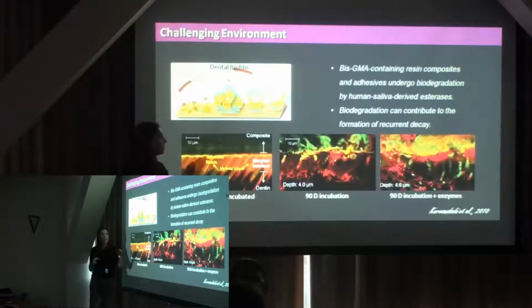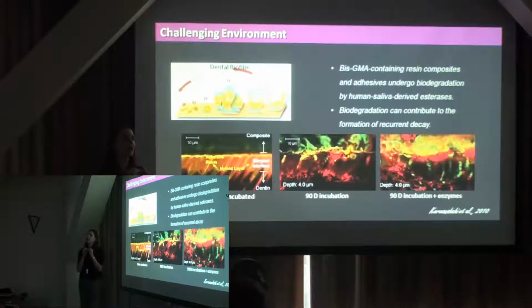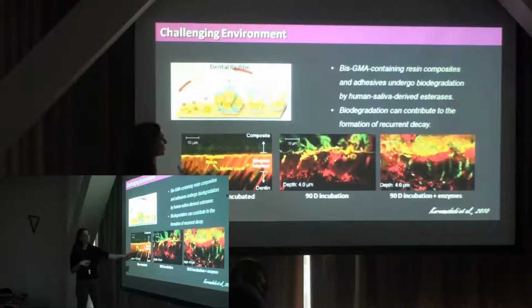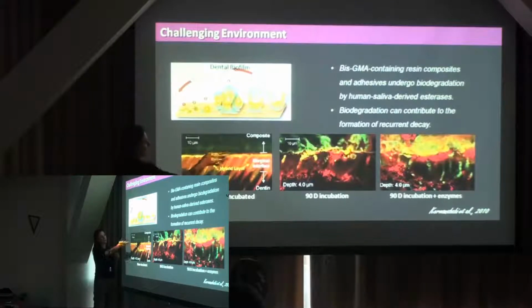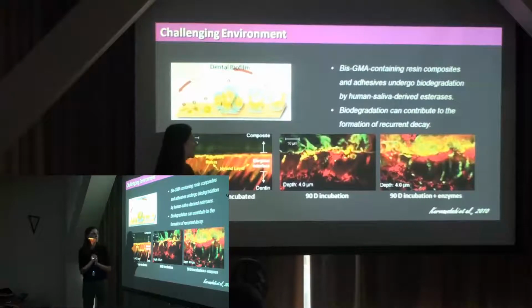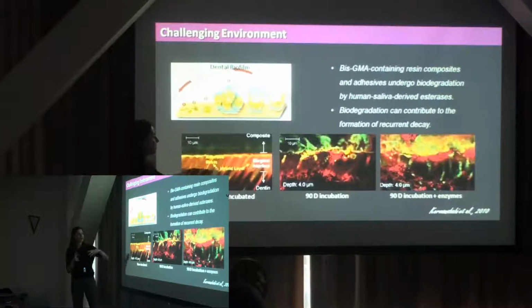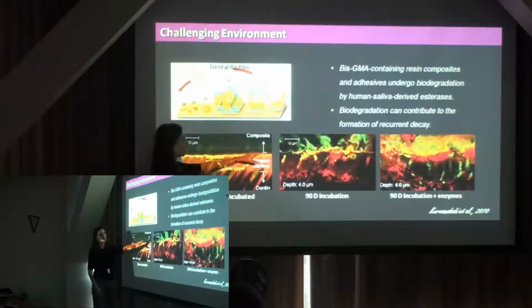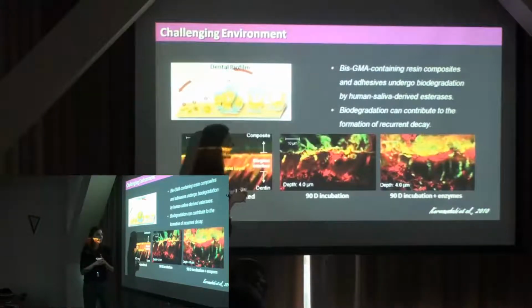So what do we know now? We know that the composites that we currently use, what's leaching out from these composites make these bugs more acidogenic. All right, so they release more acid, so you have a much more aggressive environment surrounding these restorations. All right. So this was a study that was published in 2010 from a group in Canada that basically used some fluorescent microscopy here to look at the bugs. So the green are live bugs, the red are the dead bugs.